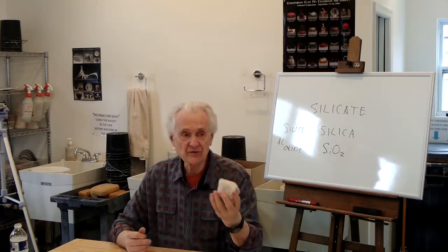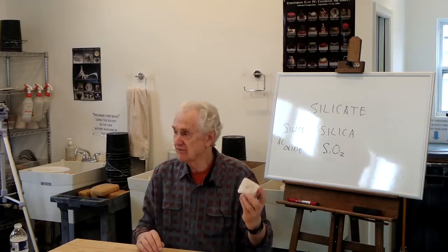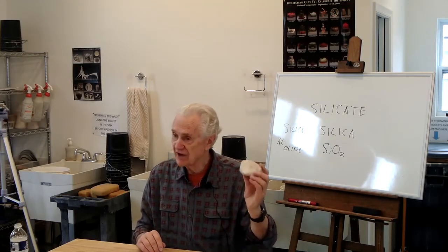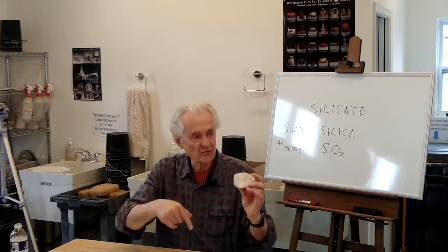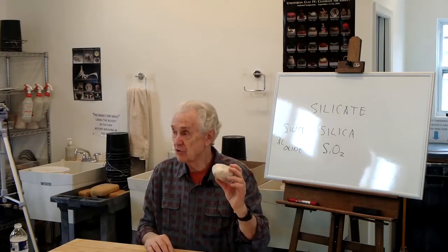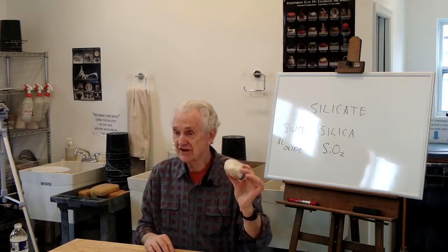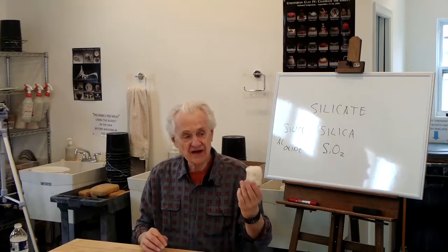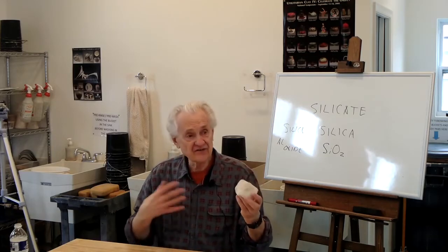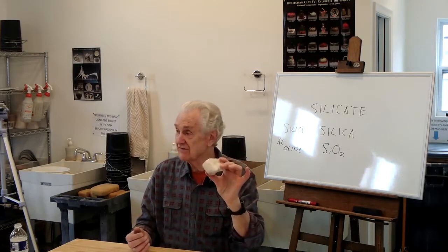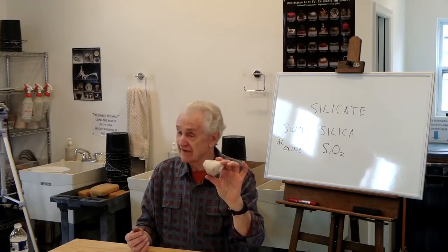So what Seger was saying was, there are certain chemical elements that I can add to this, and when I combine it, it lowers the melting point tremendously, like maybe almost half. So all of a sudden, if I combine this with a flux, now with the kilns that we have available, I can melt this stuff and turn it into a glass. So that's what the fluxes do.